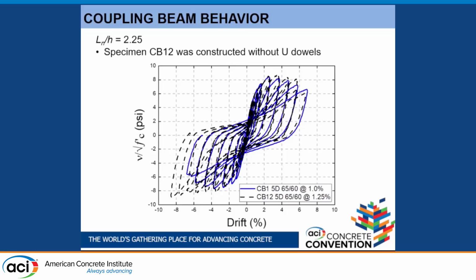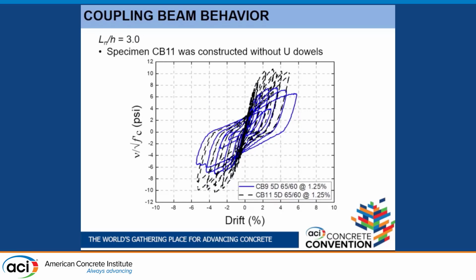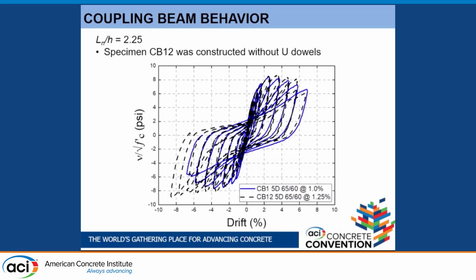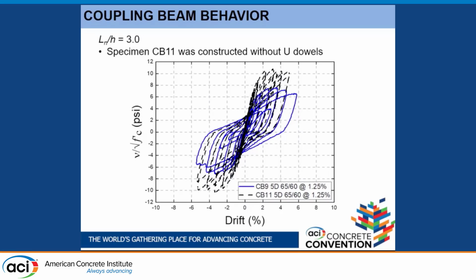Looking into the hysteresis, this is normalized shear stress versus drift response. As you can see, if you pay attention to the y-axis, this is shear stress over root of f prime c. Drift at 20% strength decay, in this case in the negative direction, went all the way to 8%. For the other pair of specimens, a similar behavior; one had lower shear stresses than the other. An important thing here is that, red and blue, one with dowels and one without, black and blue, one with dowels and one without dowels, show very similar behavior in terms of drift capacity.